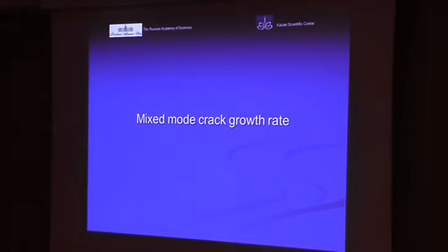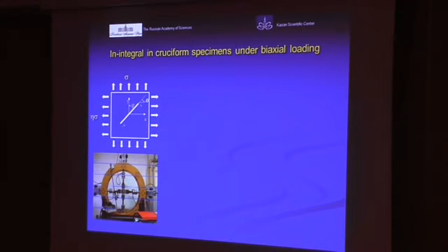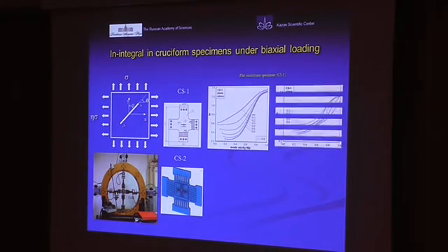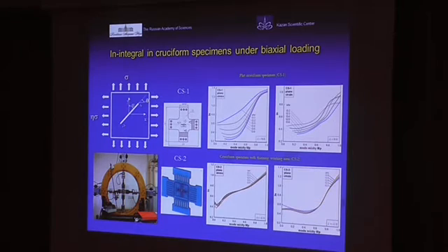So, the next application of nonlinear stress intensity factors is the problem of mixed mode crack behavior. You see, we tested, and subjected to our tests and calculations, two types of specimens: flat cruciform specimens, and cruciform specimens with a thinning area. And I would like to show you the constraint effect.